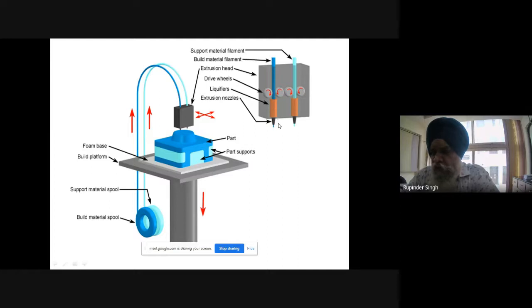This fine strand of wire comes out because of the high temperature as well as the mechanical feeding. This is just like an extrusion type mechanism. So I am getting layer by layer deposition over here, right? Once the part is built, the Z axis moves down, and I get a 3D printed part.